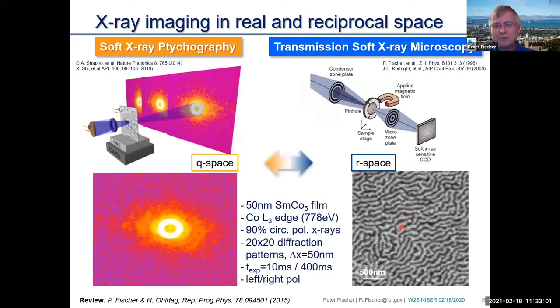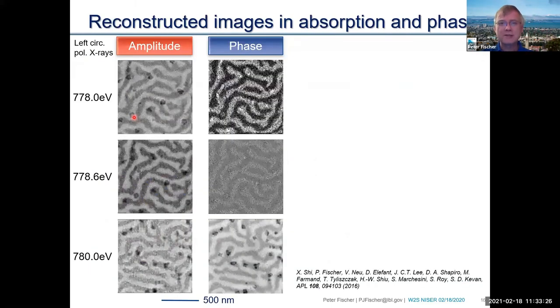Now take that same sample, which was a thin film of samarium cobalt, into a scanning microscope and do what's called the soft X-ray ptychography technique. You generate diffraction patterns, and one of them just looks like this, but you take about, I don't know, 2000, whatever. You scan across a field of view and you generate thousands of diffraction patterns, and then you start analyzing and you reconstruct the real space images from the diffraction images. And you can do this both in absorption and phase contrast, because now you have an oversampled system, and you're able to bring in by design from the analysis the phase contrast and the amplitude contrast, which you cannot do with a single optics. You would have to do some tricks to do it with optics.